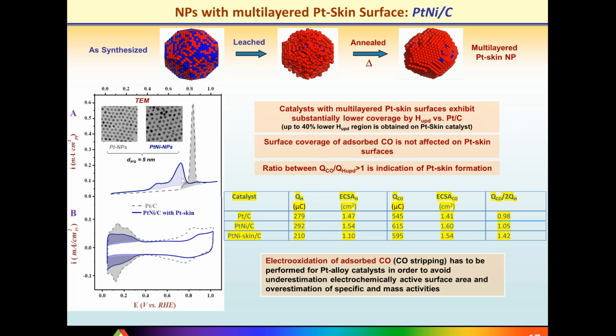So we are not talking about the shape of the curve, but we are talking about integrated charge below the stripping curve. In order to use those claims, of course, behind all of that was careful study on single crystals, and then we could switch over to nanoparticles. But the message here is whenever we start to be involved with platinum alloys, we cannot rely anymore only on hydrogen UPD as a single parameter for estimation of electrochemical surface area, because that can ultimately lead to overestimation of our activity.